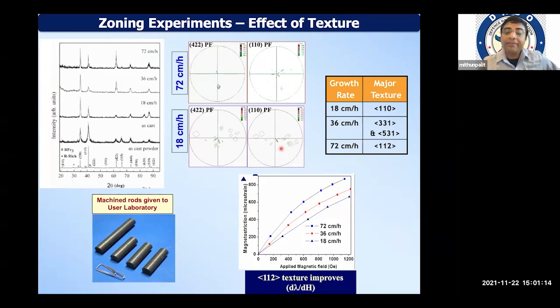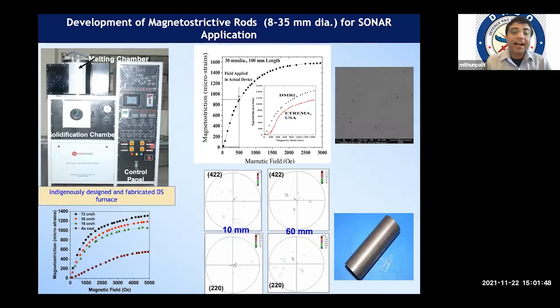And the more the intensity contours are focused towards the center, especially those reddish colors which are shown in this legend, the stronger that orientation is. We found that as the growth rate is increasing, the extent of texture in the materials becomes stronger. Accordingly, we have realized a better material. You can see this picture. This kind of actuator or transducer rods have been realized in DMRL. But this technique has a limitation. It cannot produce a very big rod. So we have resorted to another technique.